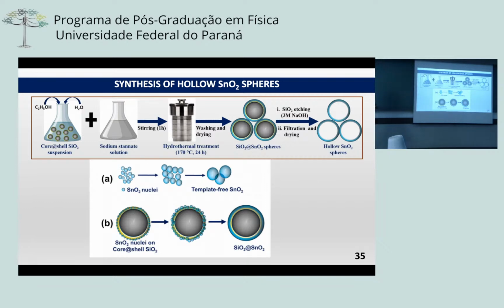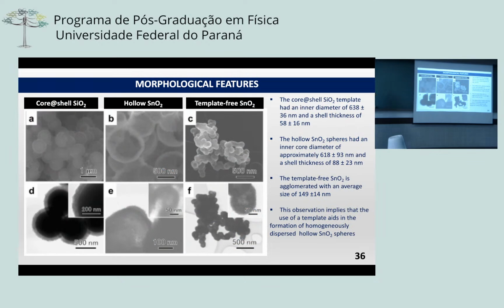So for comparison purposes, we did the same, but without using the template, to get template-free tin oxide under the same conditions. So looking at the morphological features, this is the core shell silica. Unfortunately, we didn't manage to make very small silicas. We only managed to make around 638, I think because of the centrifuge we were using. It was not a high-speed centrifuge, therefore it couldn't sort our spheres the way we wanted.